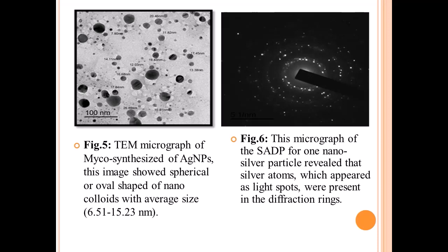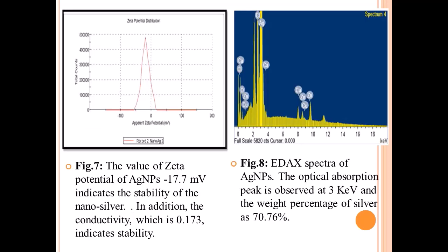Figure 6. This micrograph of the selected area diffraction pattern for nano silver particles revealed that silver atoms, which appeared as light spots, were present in the diffraction ring. Figure 7. The zeta potential value of silver nanoparticles, minus 17 mV, indicates the stability of the nanosilver. In addition, the conductivity, which is 0.1, indicates stability. Figure 8. In the EDX spectra of silver nanoparticles, the optical absorption peak is observed at 3 keV and the weight percent of silver is 70%.